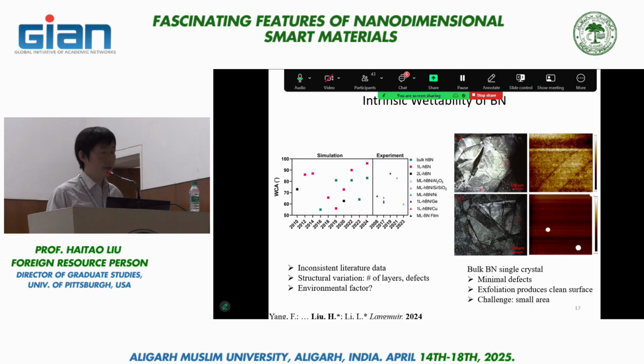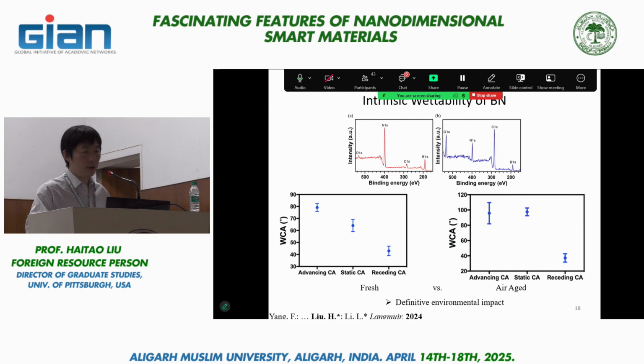Everything I showed you before was measured by a static method, basically adding a drop of liquid on the surface and then taking a picture. But you can also measure a dynamic contact angle by continuously adding liquid to that droplet or withdrawing liquid from it. Using this technique, you can get the advancing contact angle and receding contact angle, respectively. But it is sufficient to see that we saw the same kind of behavior.